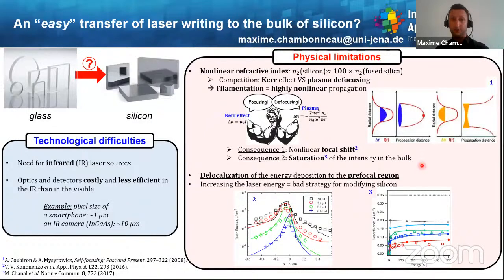Well, sadly, the answer is no. And there are two main reasons for that. First, there are some technological difficulties, especially if you want to functionalize in volume silicon wafers. As you can see here, silicon is not transparent to visible light, so you will need infrared ultra-fast laser sources. Moreover, you will probably need some optics and detectors, which are more costly and also less efficient in the IR compared to the visible. For instance, in terms of performance, here I give you an example concerning the pixel size of your smartphone, which is on the order of 1 micron. And for the best IR cameras, like InGaAs cameras, they are more on the order of 10 micron.